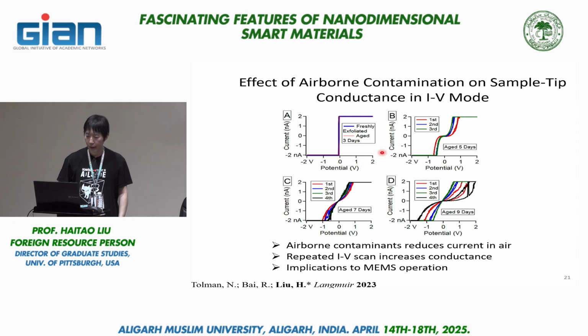In one case, we look at freshly exfoliated graphite, and what we find is if you apply even a very small voltage, the current quickly saturates. So that means the electrical contact is very good. Okay. But once you age the graphite in air for longer and longer periods of time, 5, 7, and 9 days, you start to see this reduction in the current. You apply voltage, the current doesn't go to saturation as fast, and instead you see this gradual, nonlinear IV curve. Okay? And there's some indication that if you do the measurement repeatedly, there seems to be a way to drive off those hydrocarbons within the tip.